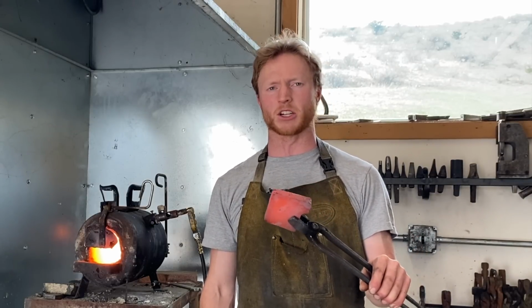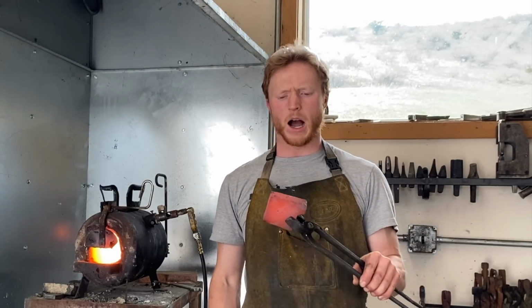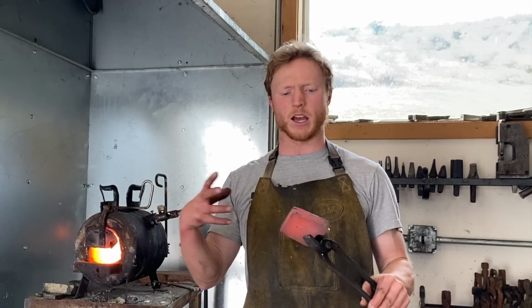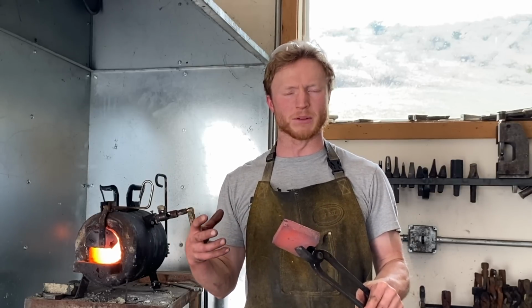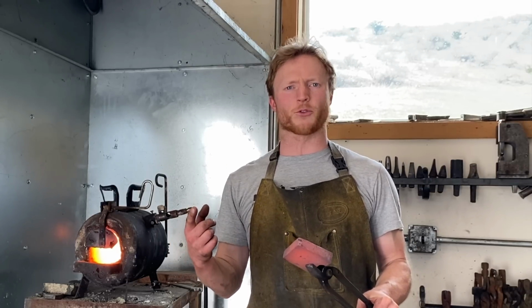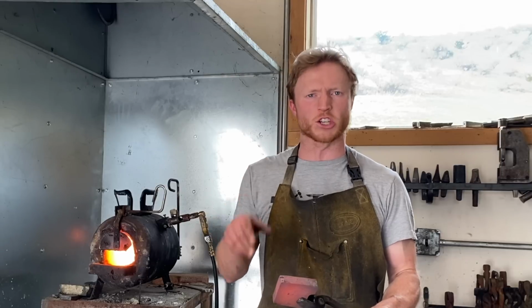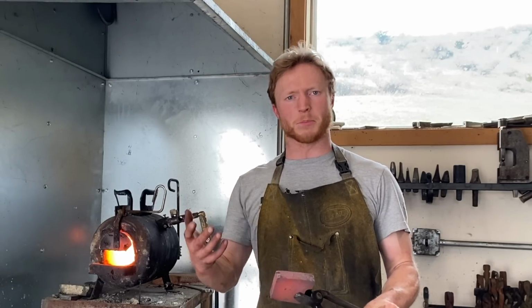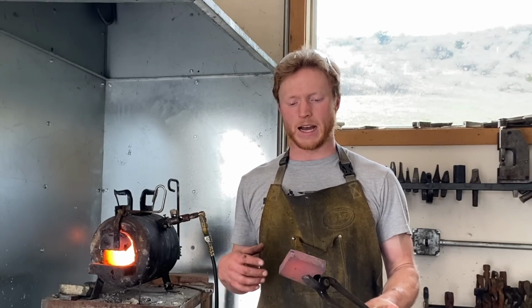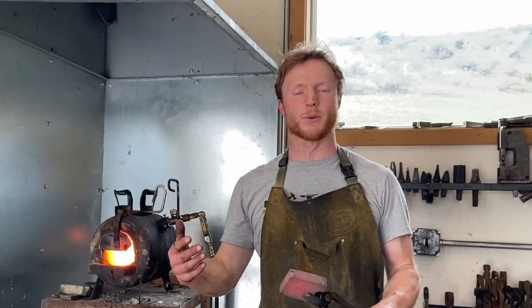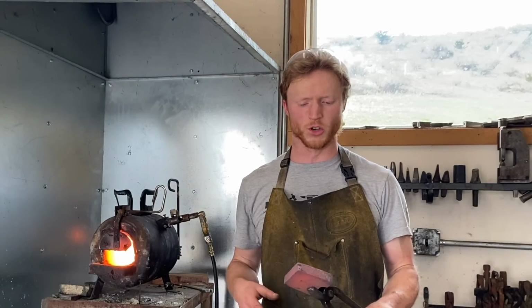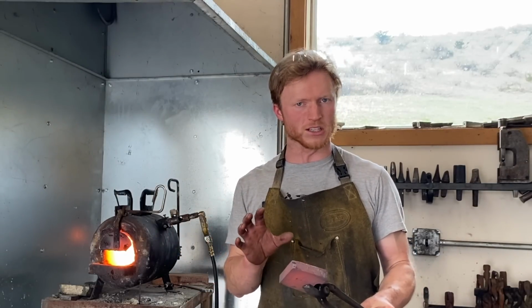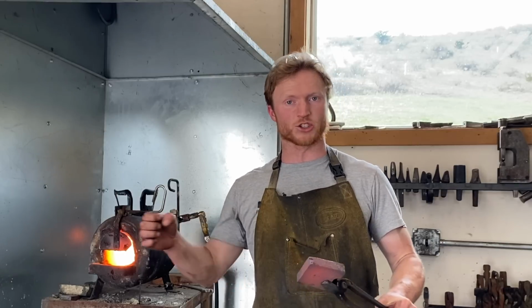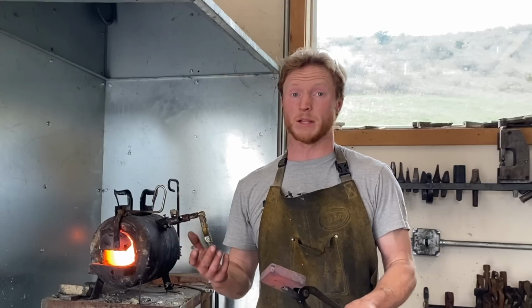Now, my one concern with this is that I might not have enough material. When I made my volume calculation, I accounted for the amount of material that I needed in the blade. What I didn't account for was the fact that I need to cut grooves across it in order to reveal the pattern that I want. And I didn't account for the extra material that I would need to remove those grooves. So I'm hoping that I added enough slop that I can just kind of stretch this blade a little bit thinner, because these blades are really thin.